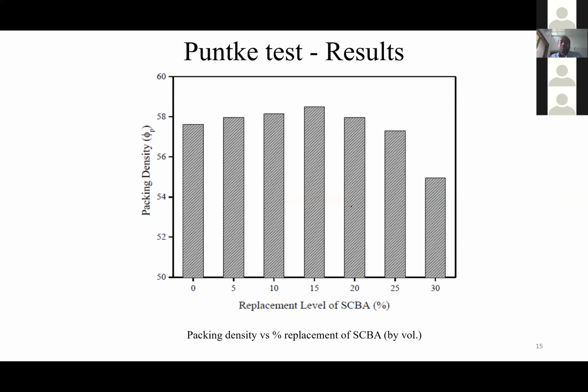So looking at the results for different replacements of SCBA, if you look at the trend, initially there is an increment and then there is a decrement. The maximum packing density was achieved at 15% replacement of SCBA with OPC. Now, why is it increasing initially and why is it decreasing? Initially, since we have ground these particles, these fine particles fill in the space between the quartz particles. Once maximum packing density is achieved, then although the particles are finer, due to their dominance beyond 15%, they create some kind of disturbance to the packed system.